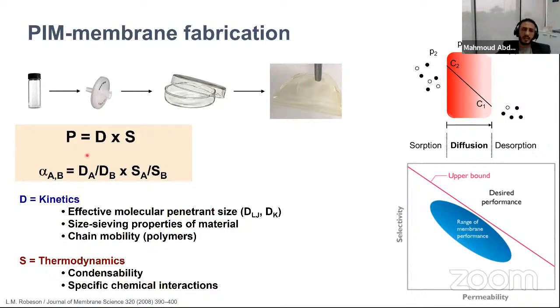The reason behind this depends on permeability. The permeability of a gas is a factor of diffusivity and solubility. Diffusivity is a kinetic factor governed by the molecular size of the gas. When we talk about carbon dioxide and methane, we know carbon dioxide has a kinetic diameter of 3.3 angstrom, while methane has a kinetic diameter of 3.64 angstrom. So these types of porous polymers can distinguish down to the angstrom level, which allows the separation to happen. Diffusivity also depends on size sieving properties and chain mobility. When we talk about chain mobility here, we mean the configuration of the structure of the polymer chains, how they are connected and how they pack on top of each other.